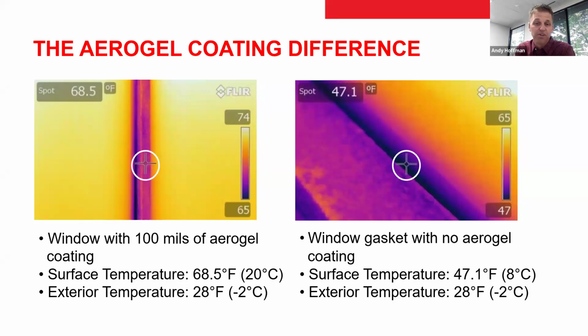It's 47.1 degrees. The picture on the left is taking a spot reading of the aluminum window frame that got the aerogel insulation coating at 68.5. So you're seeing a 21-degree difference between those two surfaces, which is why in the 9 years now that this application has been in place, they've no longer seen condensation on that frame itself. Again, those FLIR imaging cameras are a really good way to take a snapshot of the surface itself in terms of the temperature.